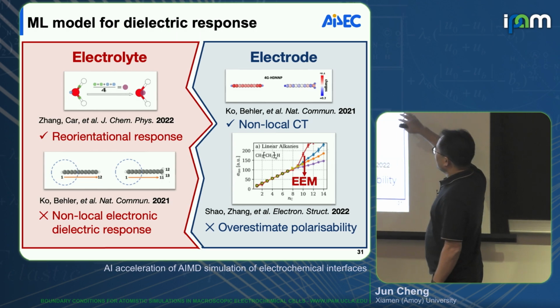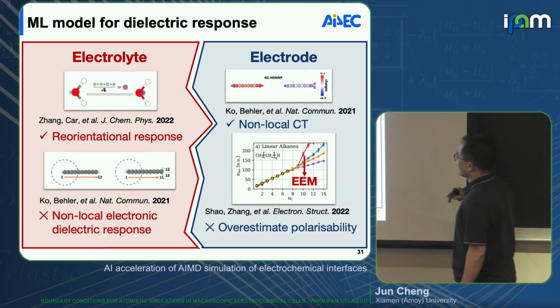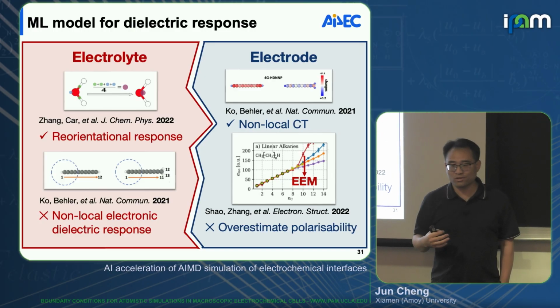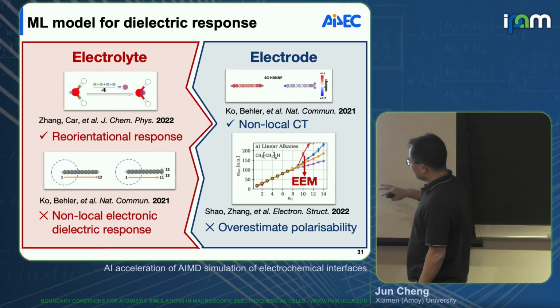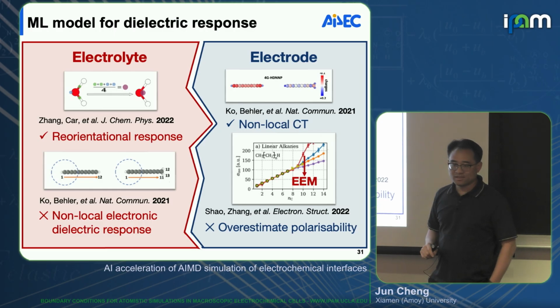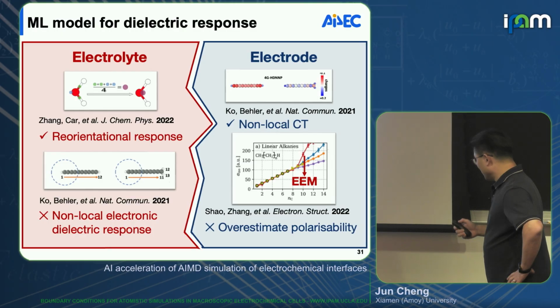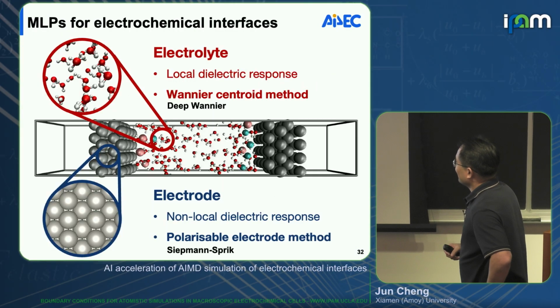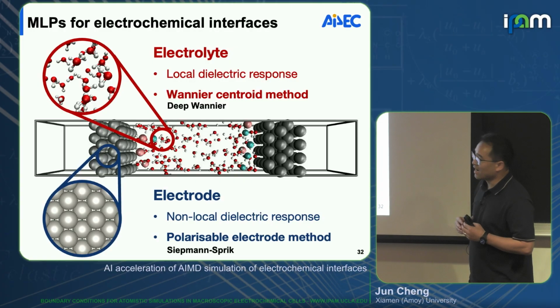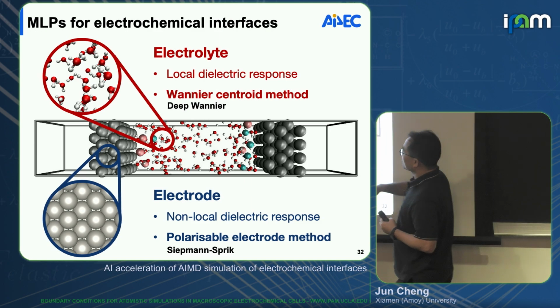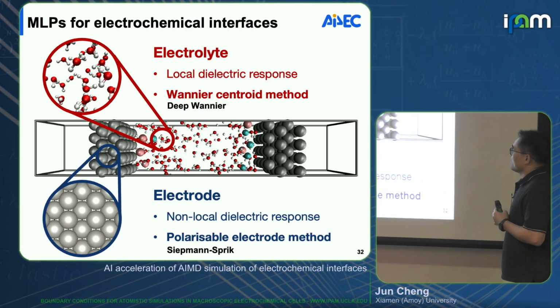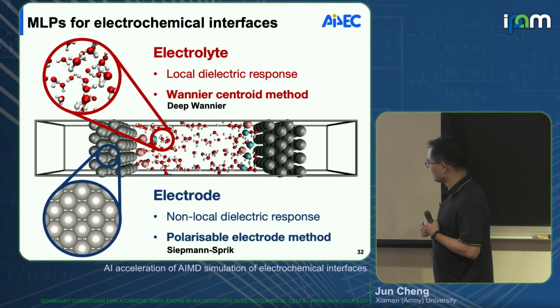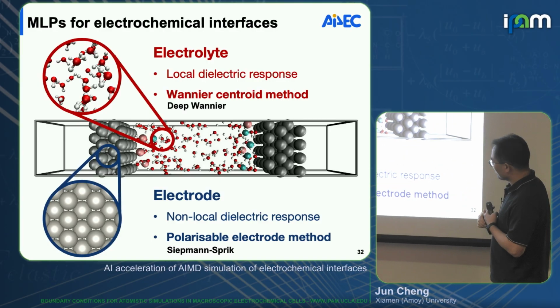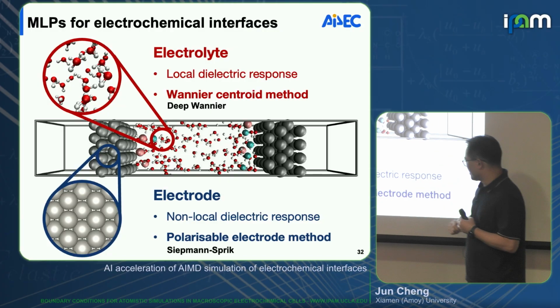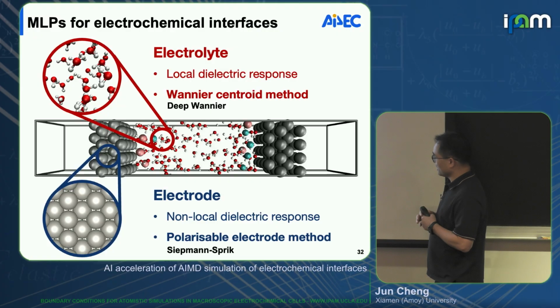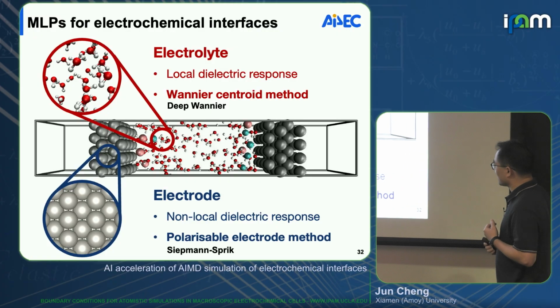For electrodes, in the community, people have developed various versions, right? Taking into account the long-range charge transfer, like the QEq charge equilibration scheme, and many other variants. But this method tends to overestimate the polarizability for insulating molecules. So they are actually complementary. Having thought about this, we came up with a hybrid representation of the metal-water interface. For the electrolyte, we're using the Wannier centroid method. It's not the same as Annabella was doing. But for the metal electrode, because it has a non-local dielectric response, in this version we're using the Siepmann-Sprik polarizable electrode method to capture the non-local dielectric response.